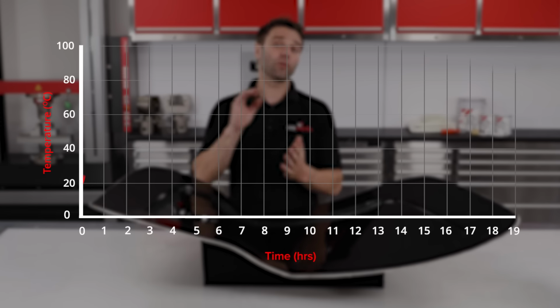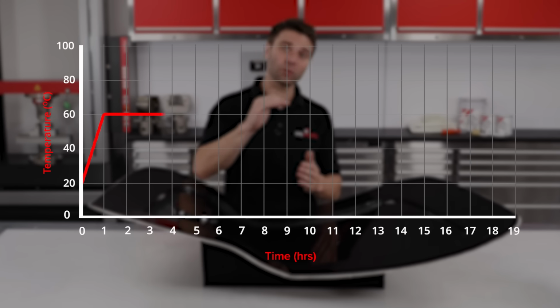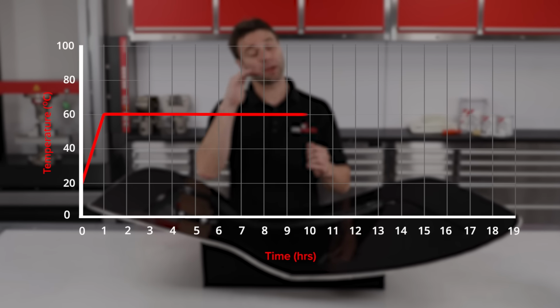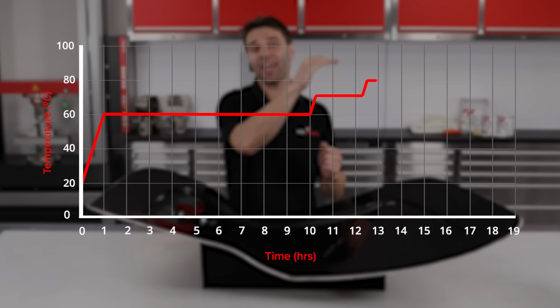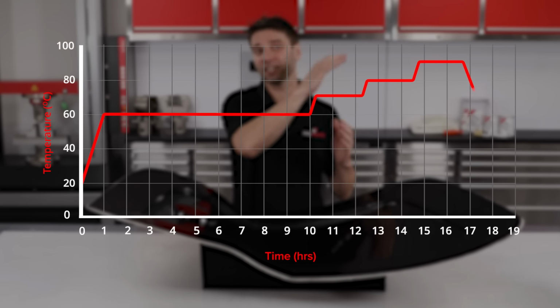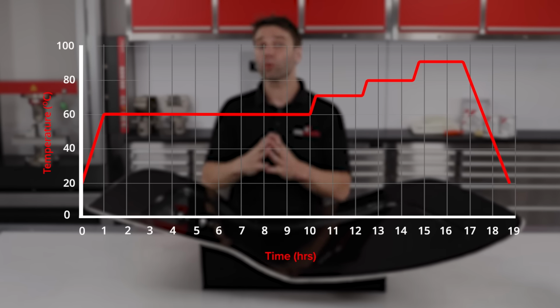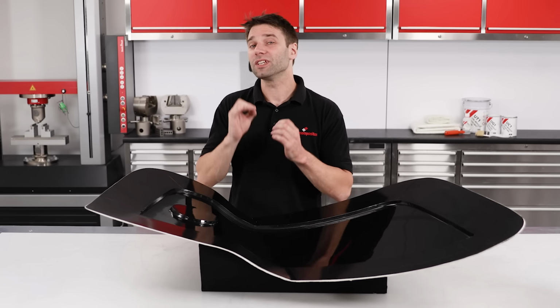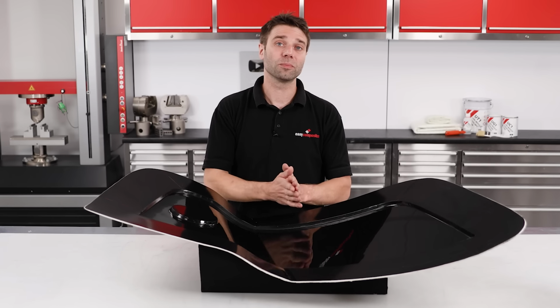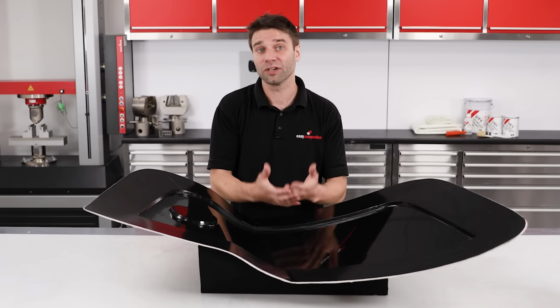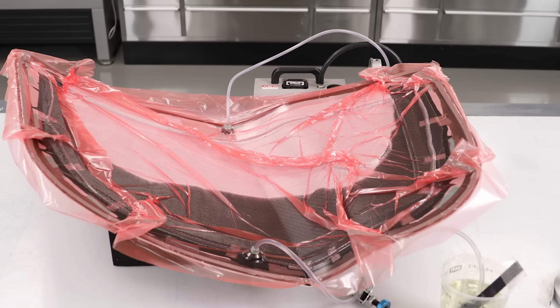The standard post-cure for Uni-Mould is 10 hours at 60 degrees C, followed by 2 hours at 70, 80, and then finally 90 degrees. But don't worry if you don't have an oven, you don't need to do a post-cure if you're only going to be using these moulds at ambient temperature for something like a standard resin infusion.